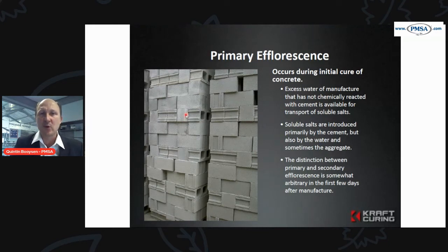And through a good quality curing system that can be reduced, and through a good quality concrete, it can also be reduced. So primary efflorescence is that excess water in the manufacturing that is not chemically reacted with the cement, and is available for the transport of the soluble salts. So it's that free water that's in the system, as we saw earlier with the blue, that this calcium hydroxide is floating around in, moving around and to the surface.